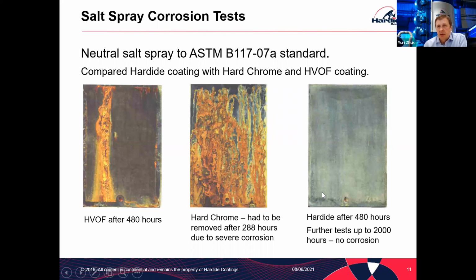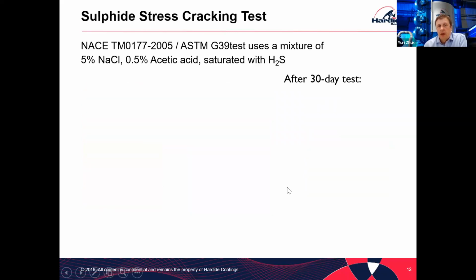So you can see that the Hardide coating did not show any signs of corrosion after 480 hours, and further testing up to 2000 hours still did not show corrosion. So it's a very dense, pore-free, good barrier against corrosion. More than that, it can protect against more aggressive media.